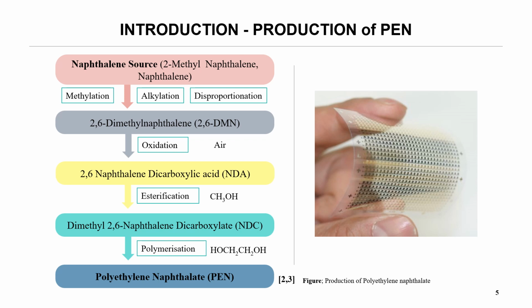The most common route for the synthesis of polyethylene naphthalate involves primarily the oxidation of a dialkyl naphthalene to a dicarboxylic acid, its esterification to dimethylnaphthalene dicarboxylate, and then finally copolymerization with ethylene glycol to produce polyethylene naphthalate. In this route, a key material is the dialkyl naphthalene, which is produced from a naphthalene source. 2,6-dimethylnaphthalene is the most preferred. However, its high cost and low availability limits the large-scale production and commercialization of polyethylene naphthalate.